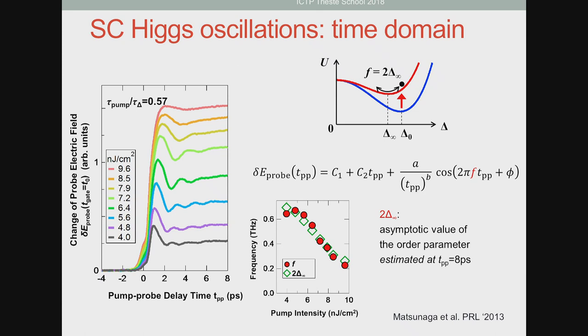The oscillations are particularly visible here at low fluence, when you exert a pump that is not too intense. If you exert a pump that is too intense, they are essentially damped. And you can extract the frequency of these oscillations. The frequency of these oscillations at low pump intensity matches very well twice the gap energy that is measured independently by equilibrium transmission measurements. So you have time domain oscillations of your transmitted electric field that have a frequency of exactly 2 delta.